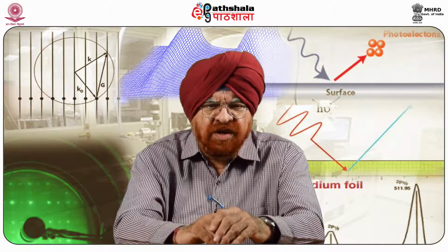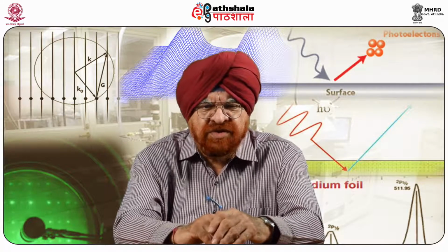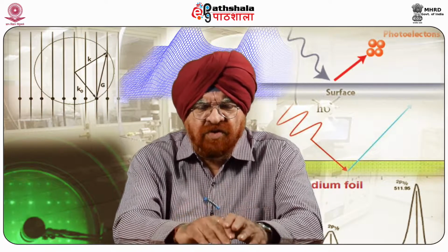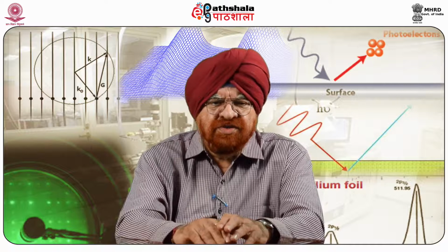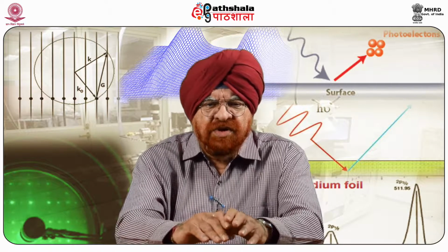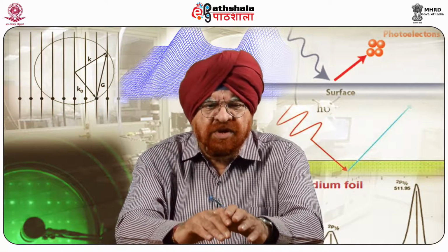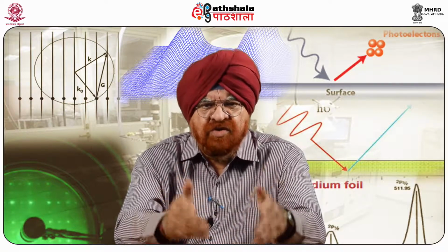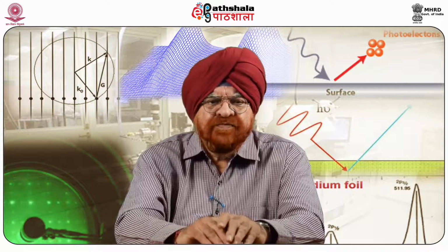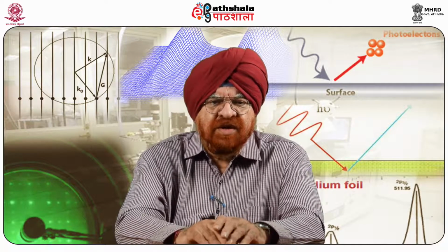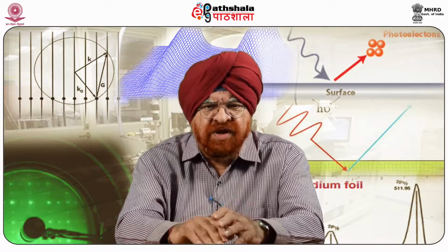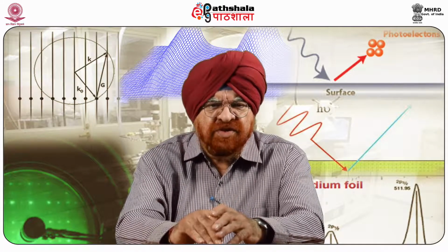However, though for clean and low indexed surfaces the calculation can even be performed on a microcomputer, the necessary computing effort grows considerably with increasing complexity. It scales, depending on the approximations used, with n^2 to n^3, where n is the number of atoms in the unit cell.